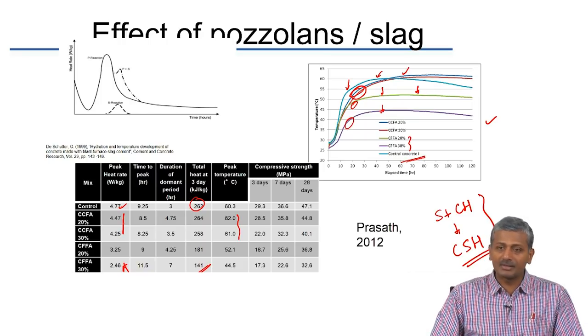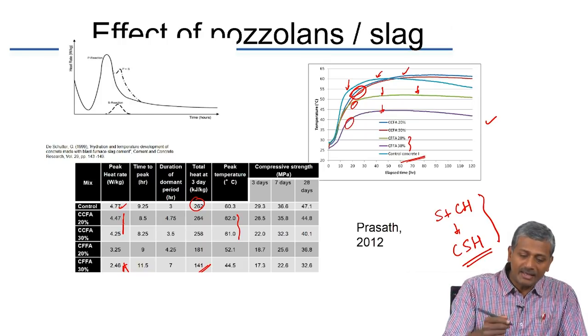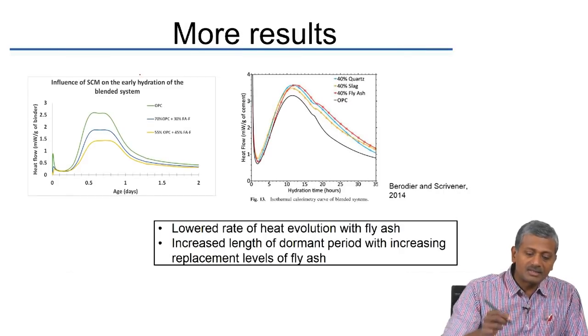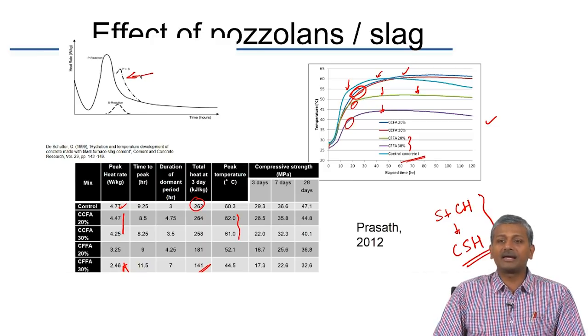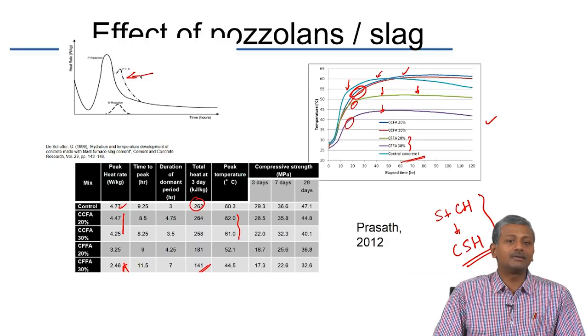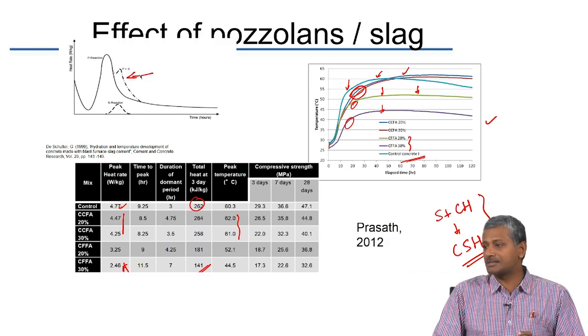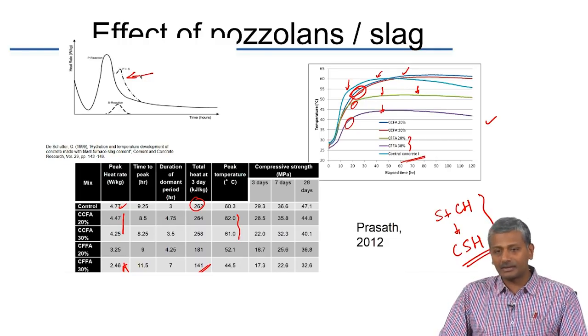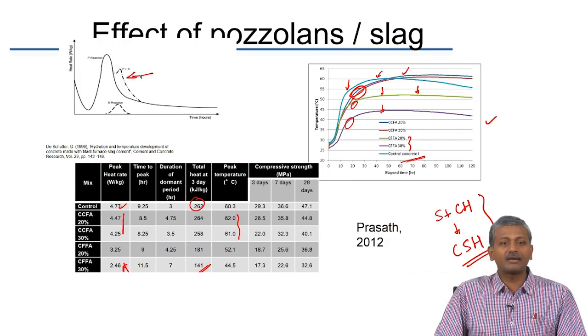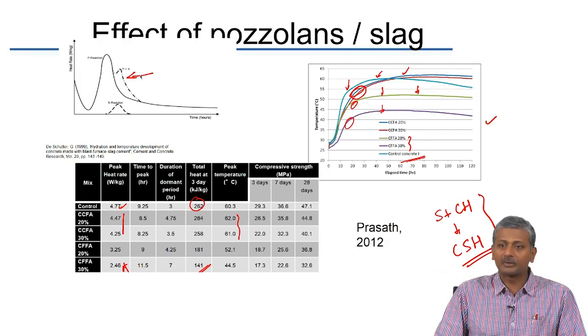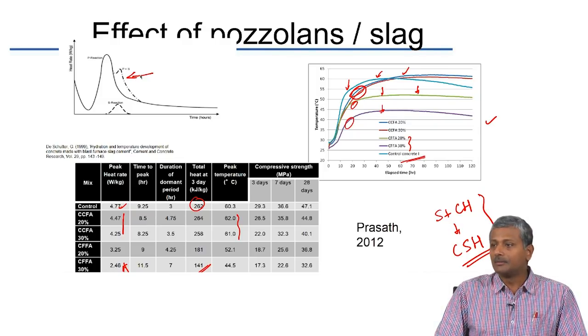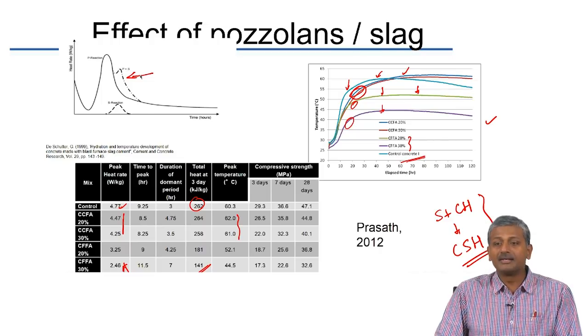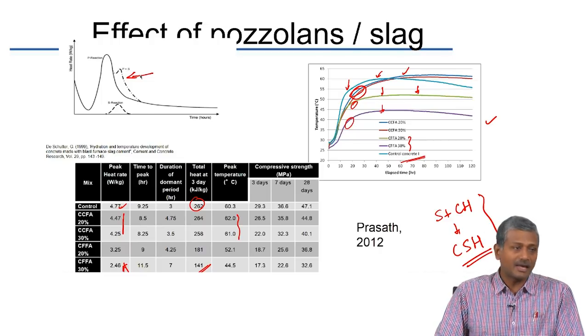Fly ash will be discussed in detail later. For slag, it has been reported that you may see an additional peak in the heat evolution pattern — a peak related to the reaction of the slag itself — especially when the slag is very reactive. In most cases slag reacts much slower than cement and may need a lot more time for the reaction to initiate.